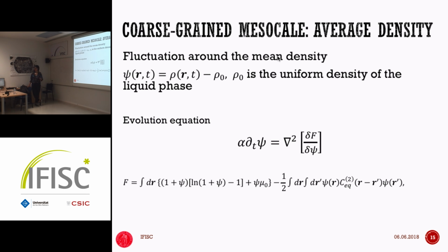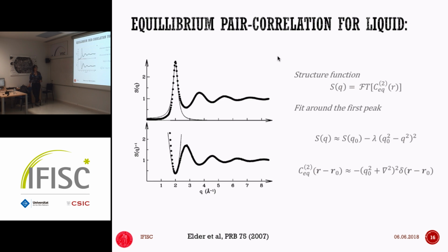So you can model crystallization by just inputting the pair correlation function for the liquid phase, okay? Now, how do we get to the phase-field crystal is to look at the structure function, which is the Fourier transform of the pair correlation function, okay, for a typical liquid. And then we do a gradient expansion. So basically, in Fourier space, we do an expansion around the maximum, because the maximum is going to give us the perfect order, and then you have the perturbation from the disorder, right?